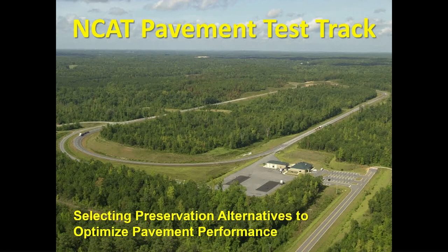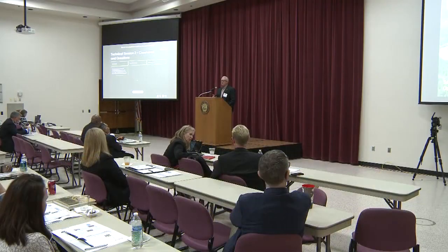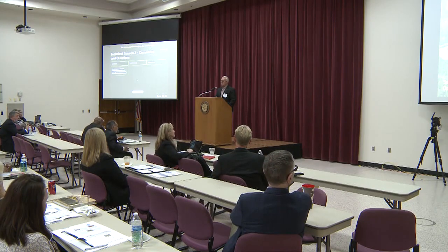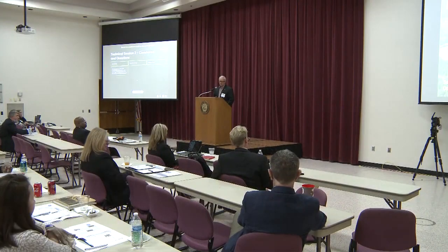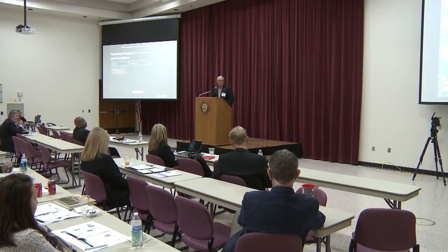ODOT is also participating as a partner in what we call our cracking group experiment, and in that study we're not just looking at the IFIT test and the IDEAL test that he mentioned, but we're looking at a battery of tests in the laboratory that are supposed to assess the durability and the cracking potential of mixes. So we have test sections on the track, and we pulled a massive amount of material samples when we built those sections, and we're running a full battery of tests at a bunch of different aging and conditioning characteristics, so that we can see what matches the differences that we see on the test track.